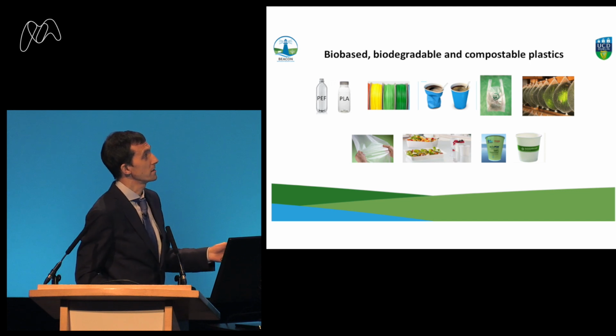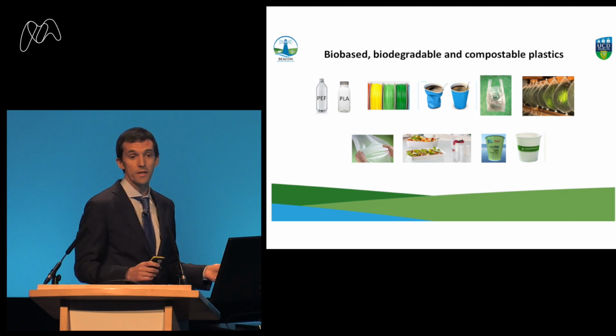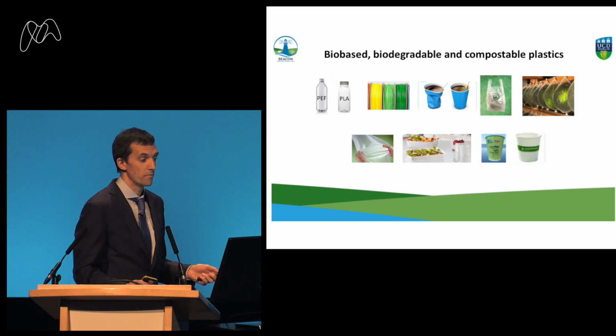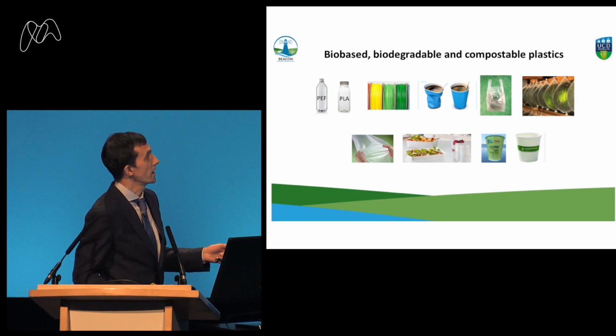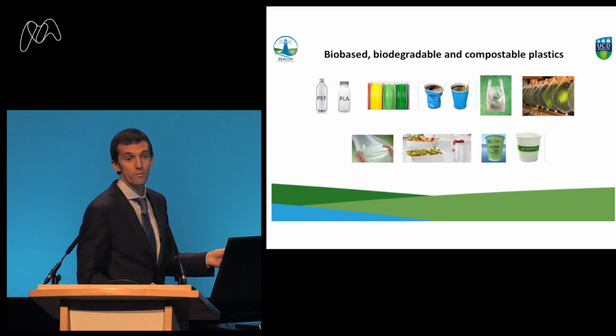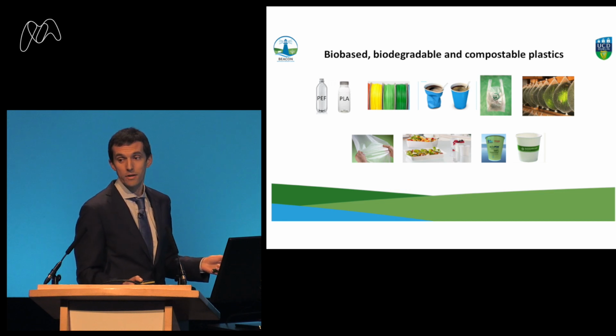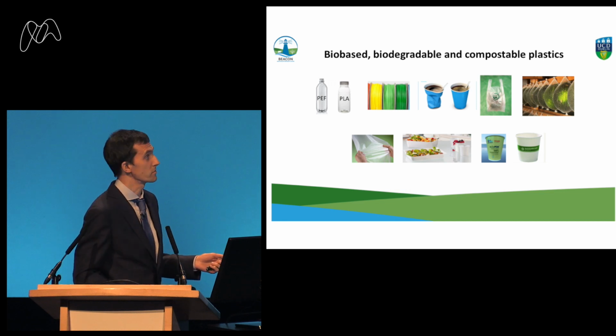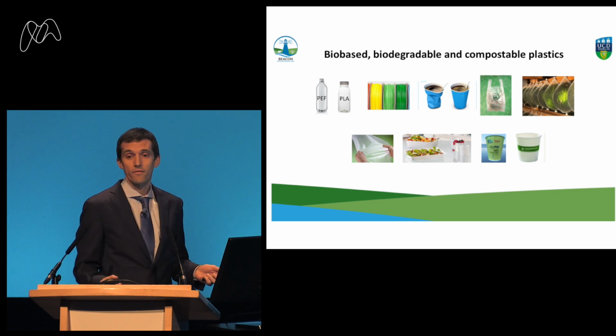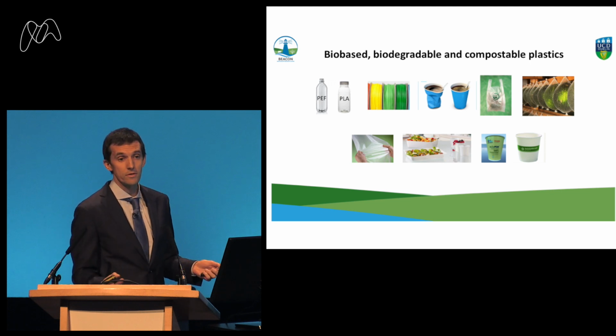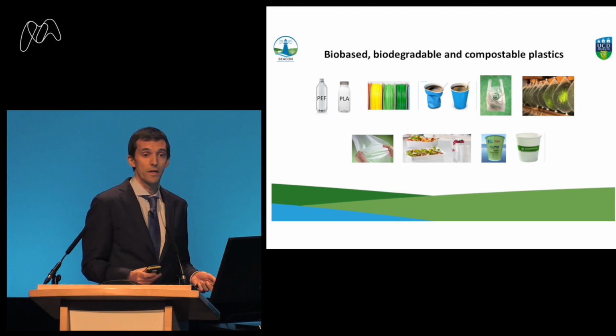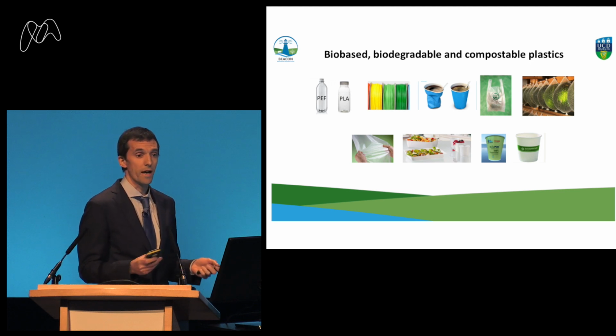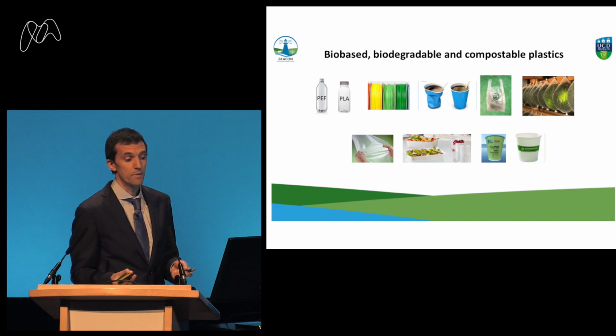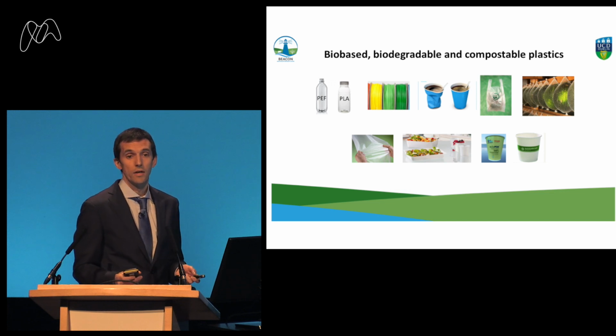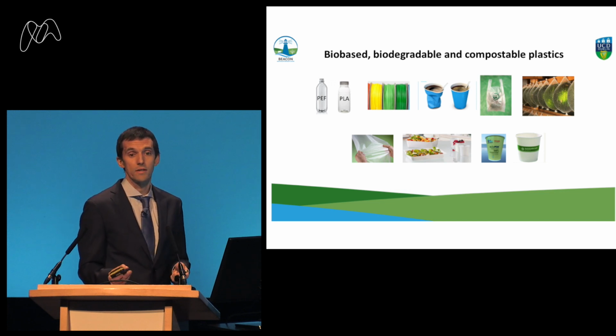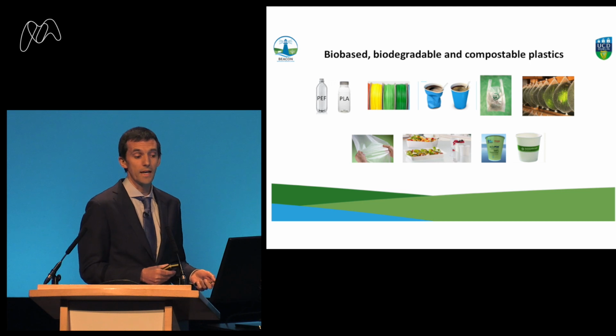And you can blend these polymers. So you can blend PLA with PBAT, PLA with other polymers to make composite materials. And we don't know, actually, if some of them are biodegradable. And we did the study, and we'll show you the results of that now. And you also have, for example, coffee cups that are made out of cellulose and made out of cardboard. And the inner lining will have PLA or PBS. Mitsubishi, for example, make a biodegradable cup that has PBS, polybutylene succinate, and actually mixes it with PLA as well.